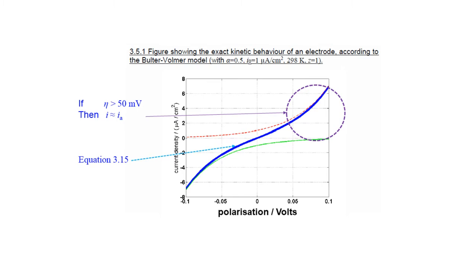And we do want to make it simpler, because at the moment it's a sinh or hyperbolic sine curve, or it's got two exponential terms in it. It's more complicated than we want to have to deal with. So what we will do is work out how to simplify it, by spotting that equation 3.15, the forward process minus the reverse process, is an exponential growth minus an exponential decay. Therefore, when the polarization is at least slightly positive, if it's at least 50 millivolts positive or more, then really the only significant term is the forward term. So in other words, for moderately significant positive polarizations, the complete equation, the thick blue curve, is approximately well described by just the forward process, the dashed red line. So we can simplify from a sum of two exponentials to just the forward exponential.